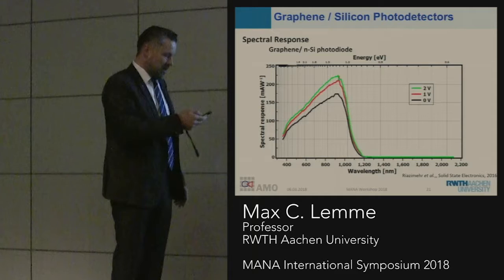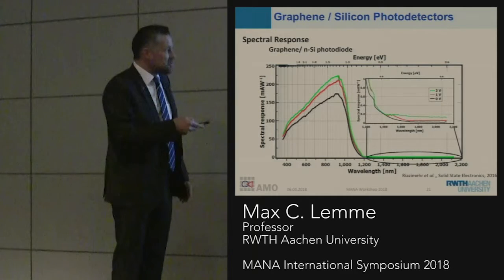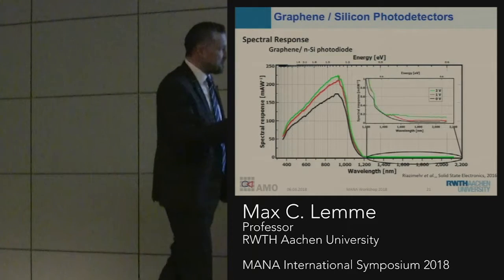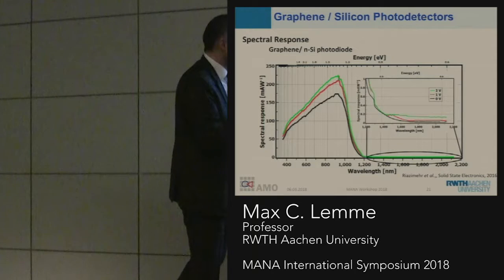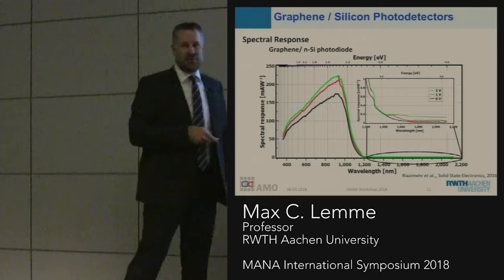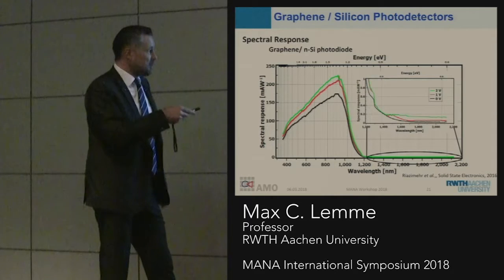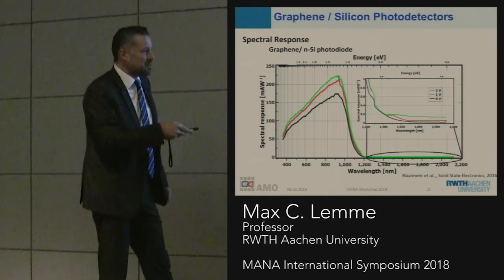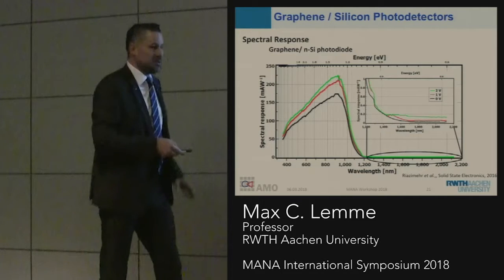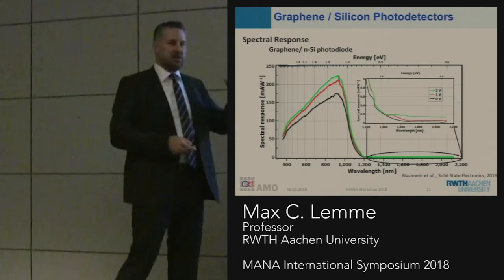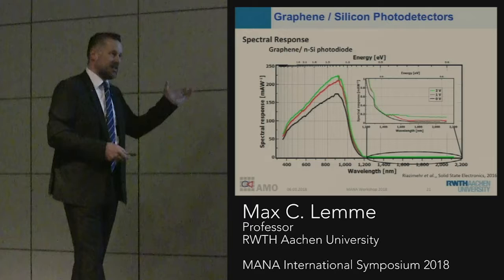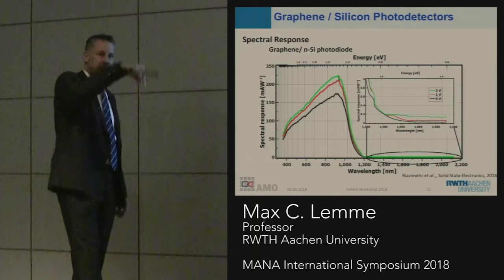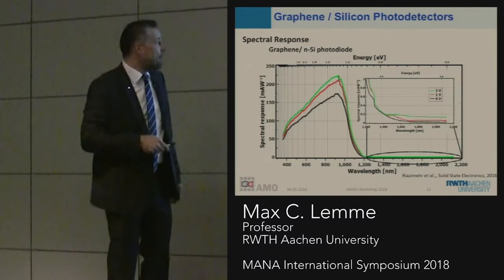But if we look into the infrared region, we also see a bias-dependent photoresponse which is about 1 per mil of the original response in the silicon. This is the graphene actually absorbing in the infrared. So we do see some tail here, but it's 1 per mil of the original signal - again, very weak because we come from a vertical direction.